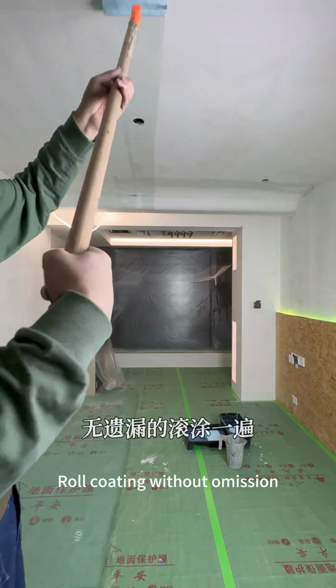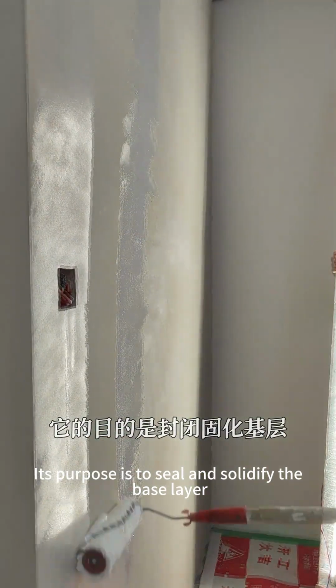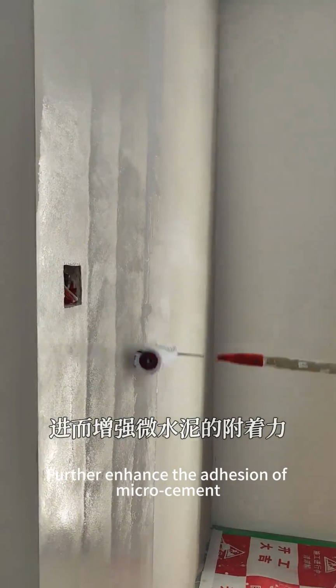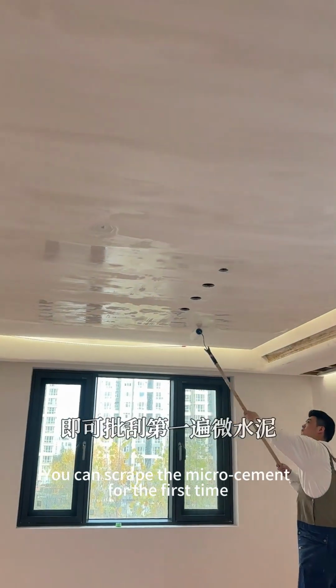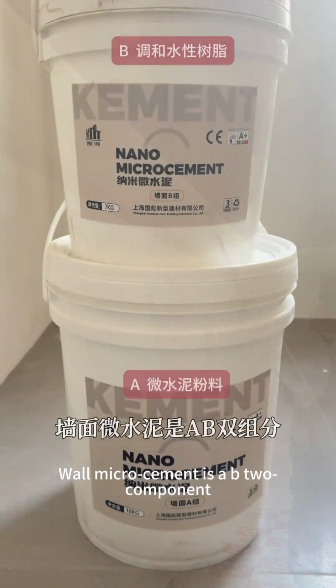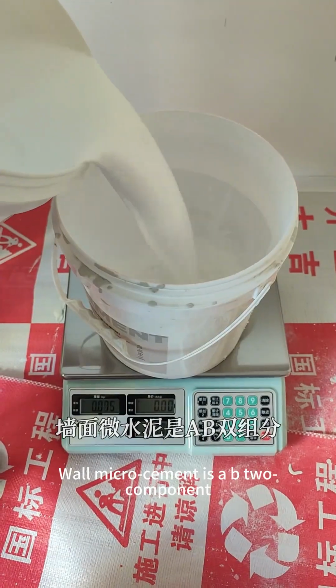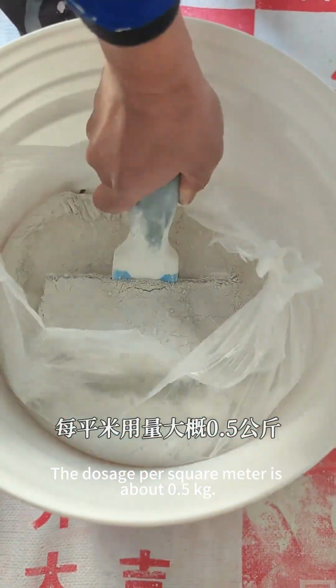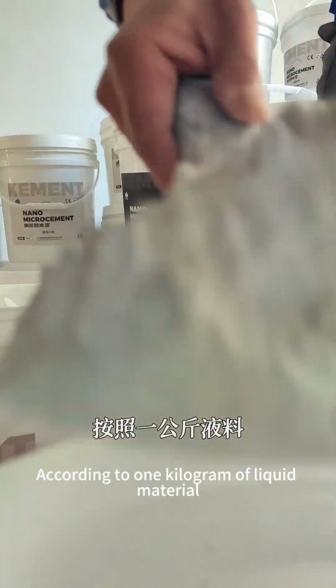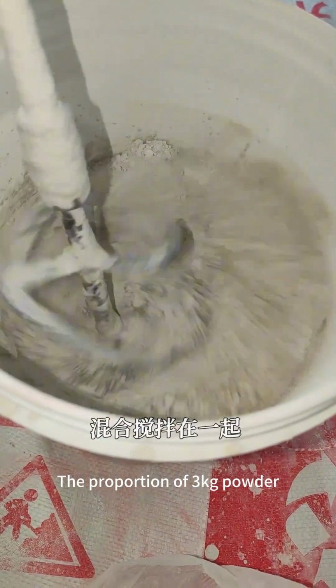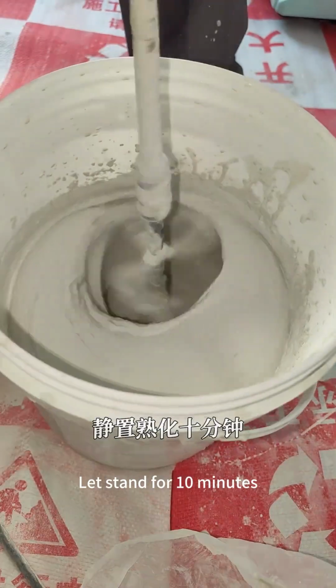Roll coat without omission. Its purpose is to seal and solidify the base layer and further enhance the adhesion of micro cement. Let dry for 20 minutes, then you can scrape the micro cement for the first time. Wall micro cement is an A-B two-component. The dosage per square meter is about 0.5 kilogram. Mix 1 kilogram of liquid material with 3 kilograms of powder and stir together. Let stand for 10 minutes, then stir well a second time and you can use it.